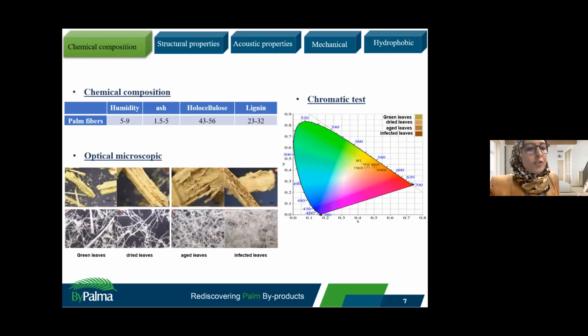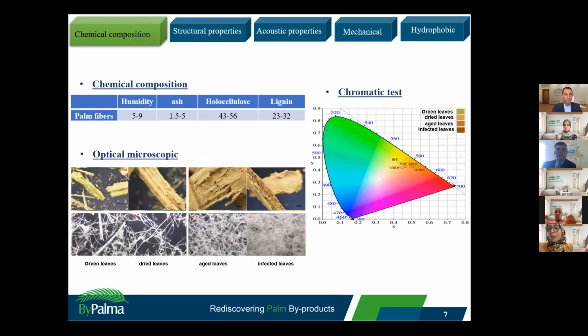So before the extraction of the palm fiber from the palm leaves, we made a chemical composition of grounded fiber in order to have an idea about the state of cellulose fiber inside our palm leaves, and to successfully choose the suitable palm leaves to produce a long fiber with the higher properties. As you see in the table, the results show that the chemical composition showed the amount of cellulose is around 50%.